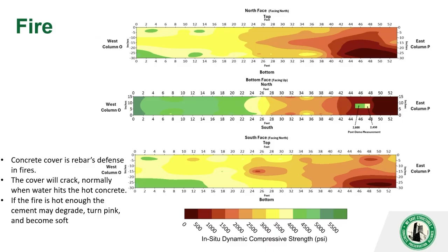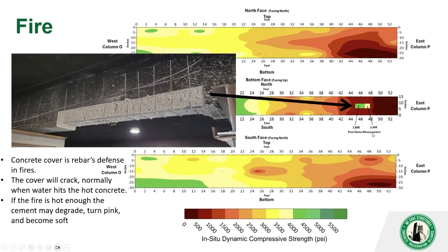And then we have fire. This is that case I showed you earlier. If you look at the beam, the fire was down here on this end. This is the beam bottom. This is the north face, and here's the south face. And you can see right underneath this area is where the fire was. Well, what we did is once we tested it, this was using impact echo. You get the strength of the concrete surface. When we sounded this with a hammer, the entire thing was hollow. It sounded like just blah.